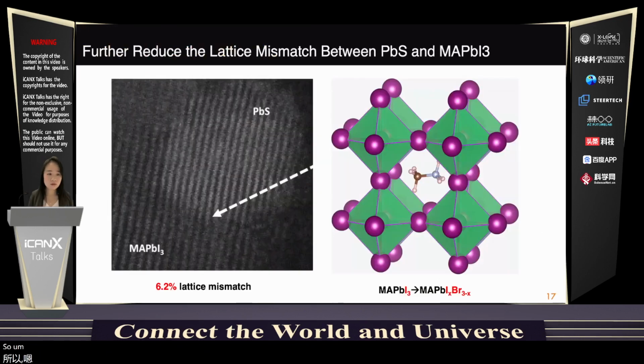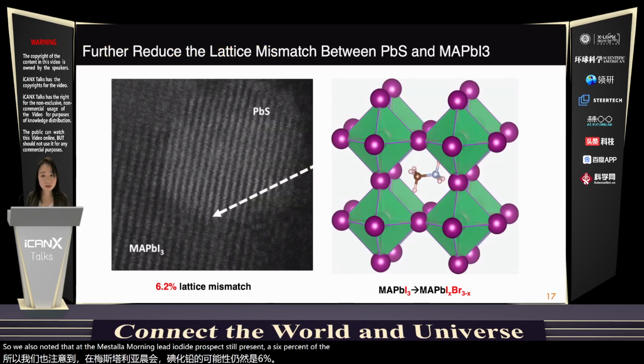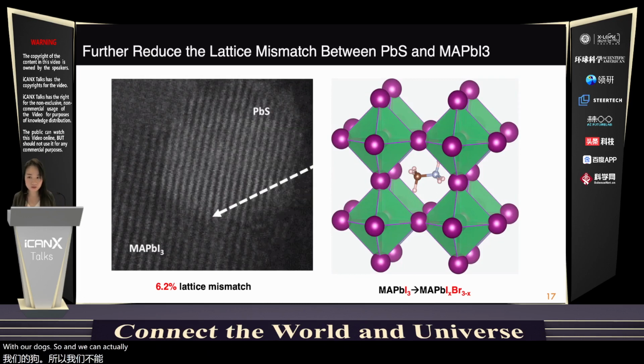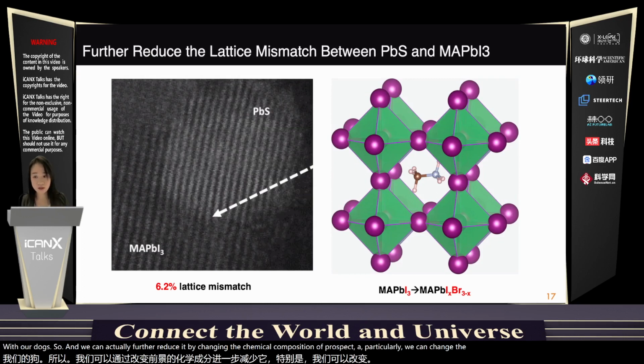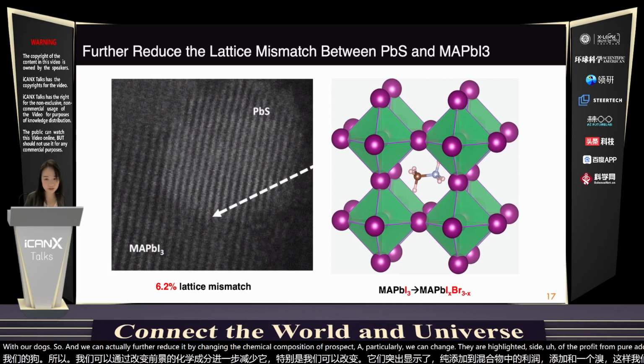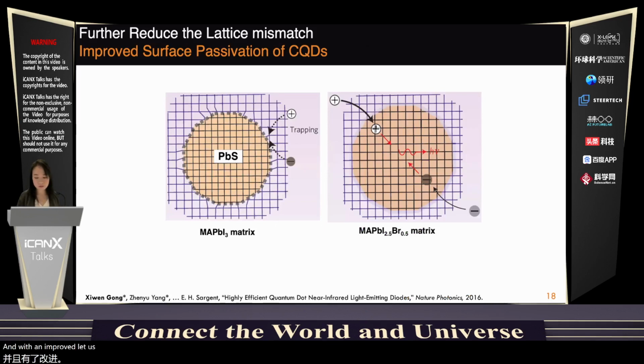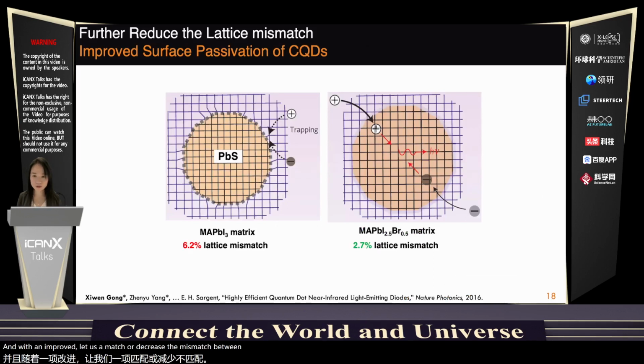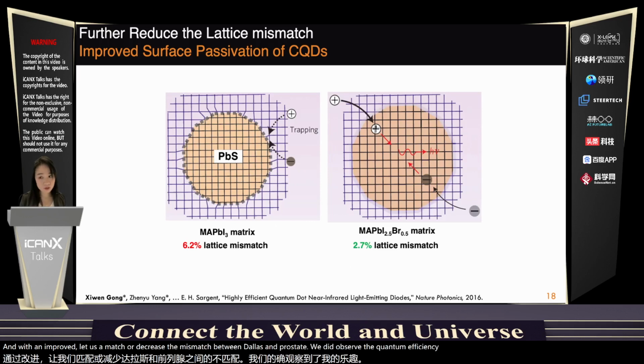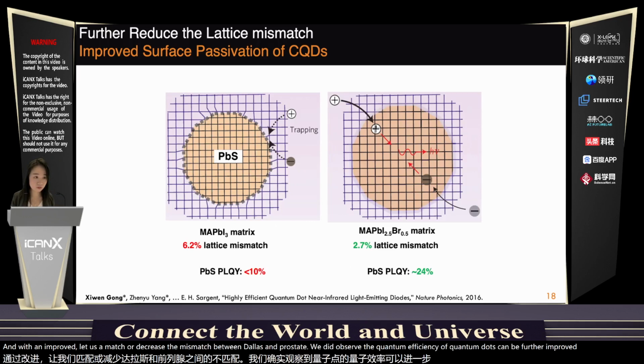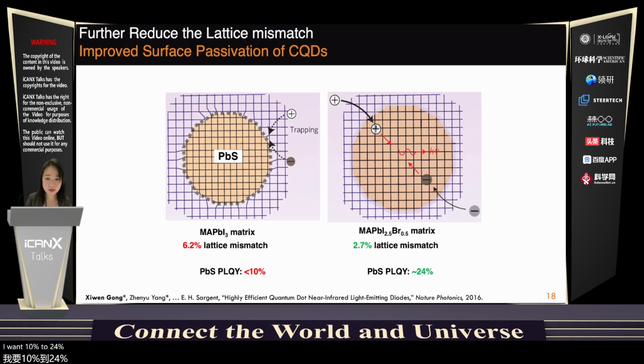We also note that the methyl ammonium lead iodide perovskite still presents a 6% mismatch with our dots. We can actually further reduce it by changing the chemical composition of perovskite. Particularly, we can change the halide side of the perovskite from pure iodine to a mixture of iodine and bromine so that we can tune their lattice size. And with the improved lattice match, or decreased mismatch between dots and perovskite, we did observe the quantum efficiency of quantum dots can be further improved from around 10% to 24%. And that represented the highest PL quantum efficiency of near-infrared dots at the time of this work.